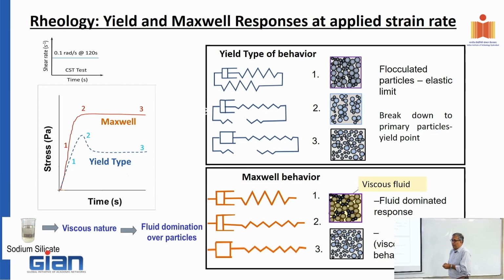What about the Maxwell flow behavior? The way I would show a Maxwell is that this parallel spring is not present. So when I start pulling on it, the resistance that I get is purely from the spring and dashpot. It continues to open, and then it eventually continues to open once you get into that constant velocity regime. So this is an idealized representation of a Maxwell behavior. Here, the resistance increases to a peak and then it stays constant. It's continuously deforming, basically. It doesn't rest.